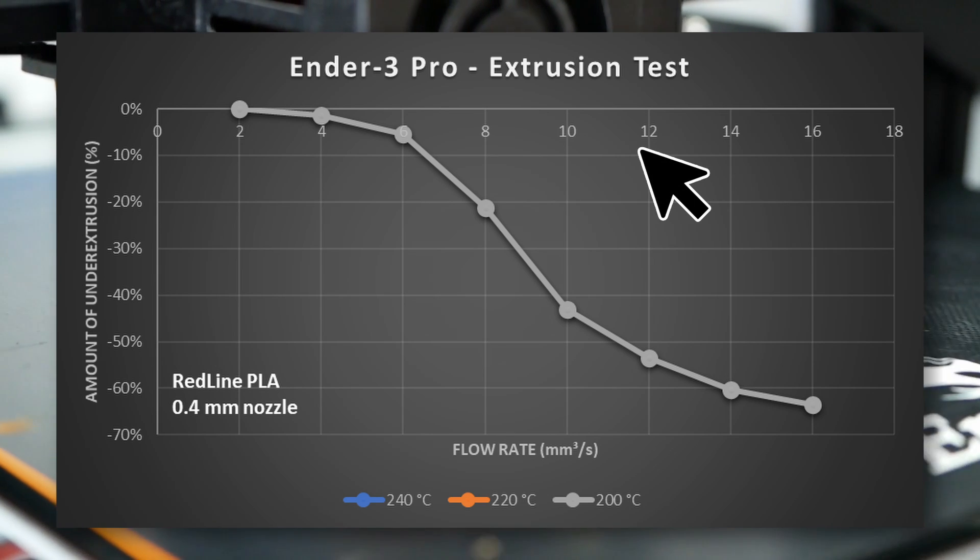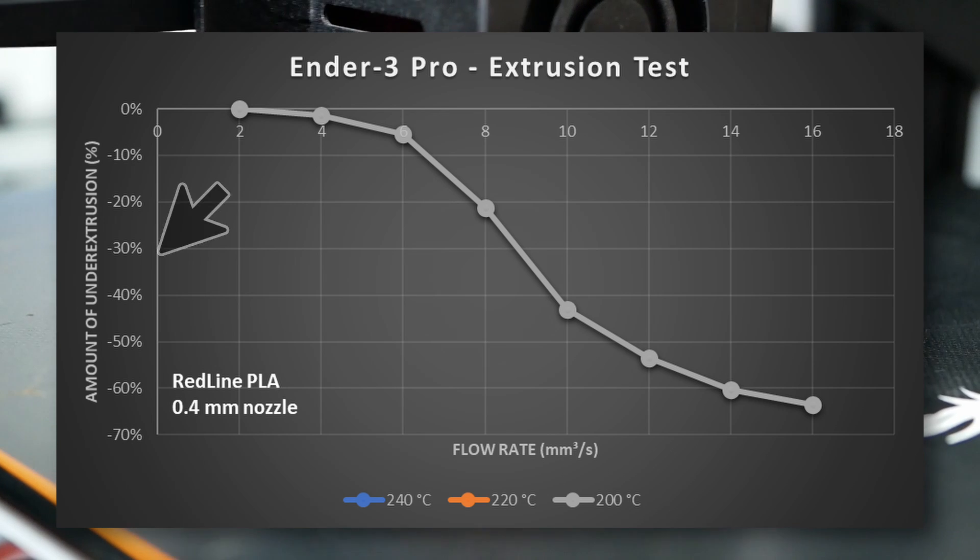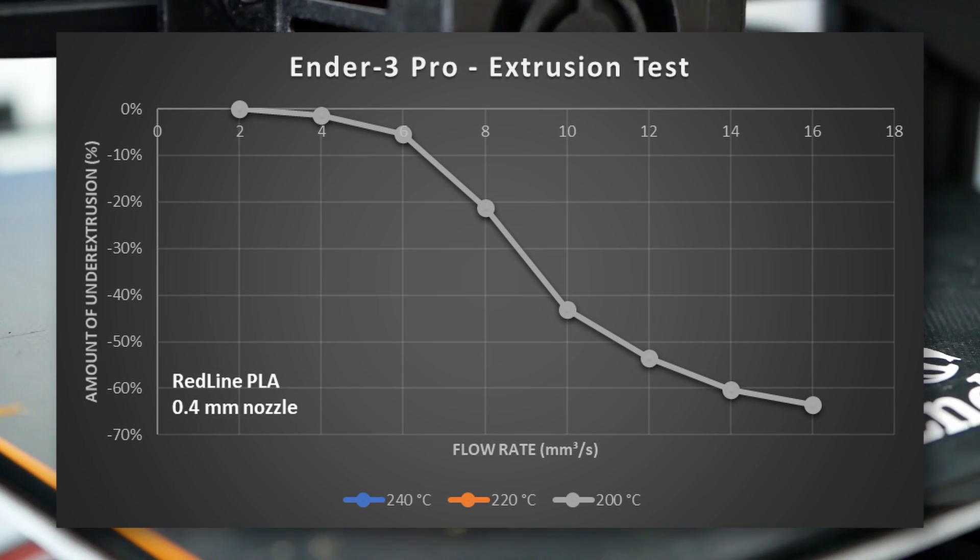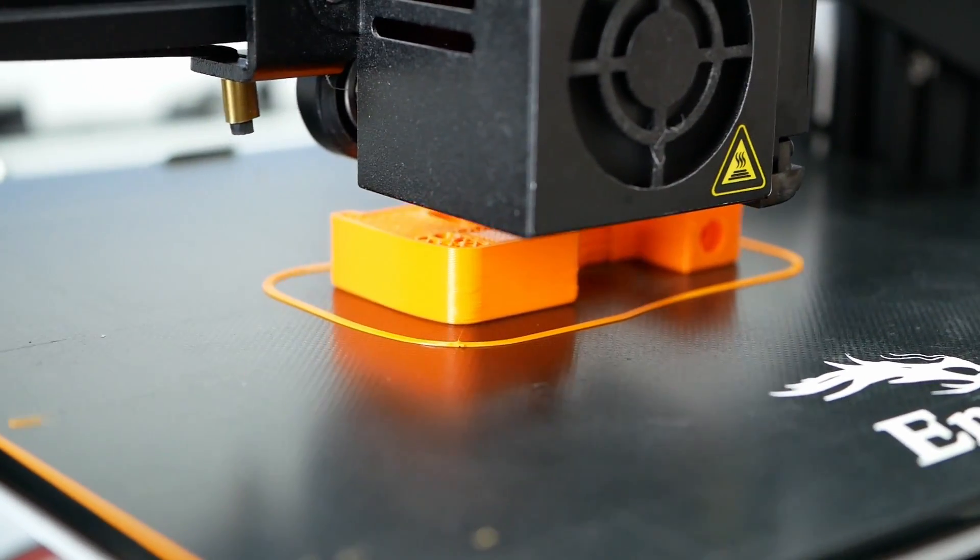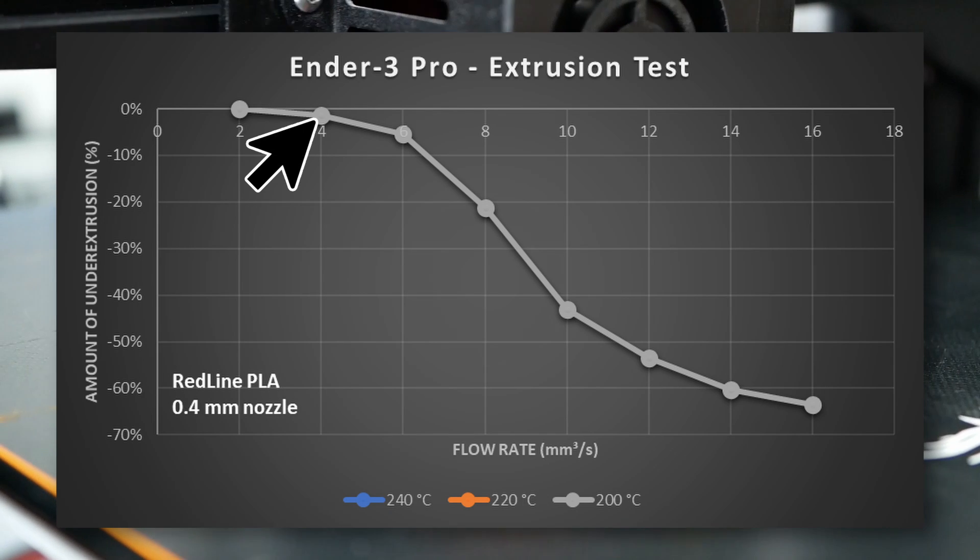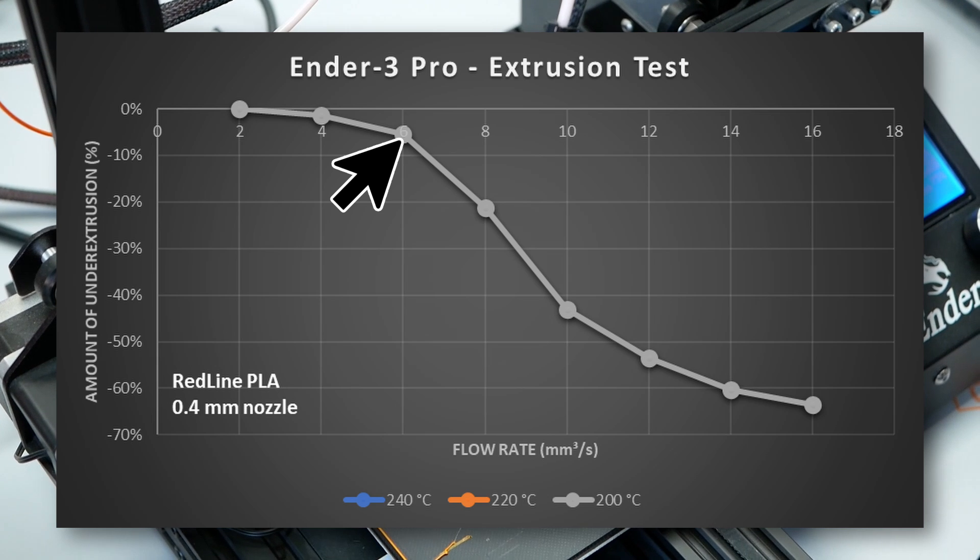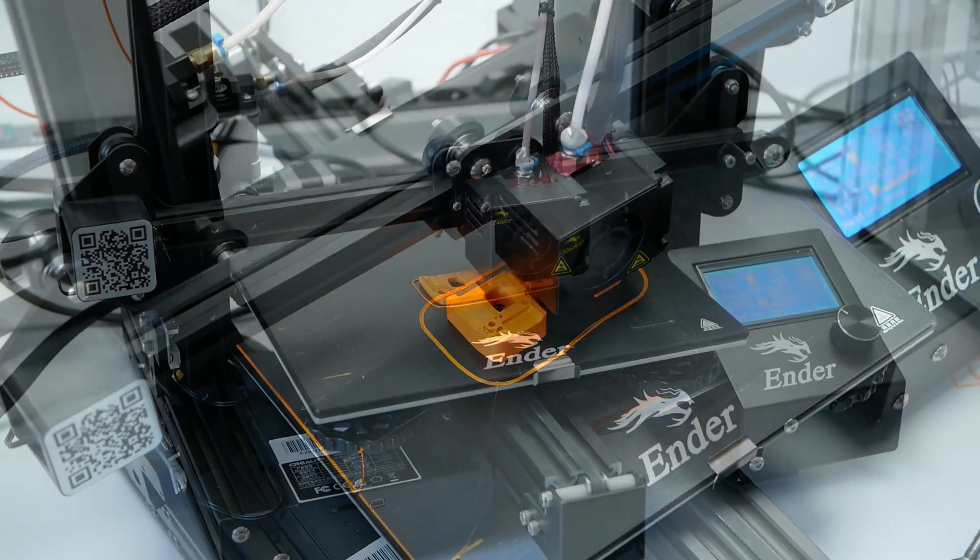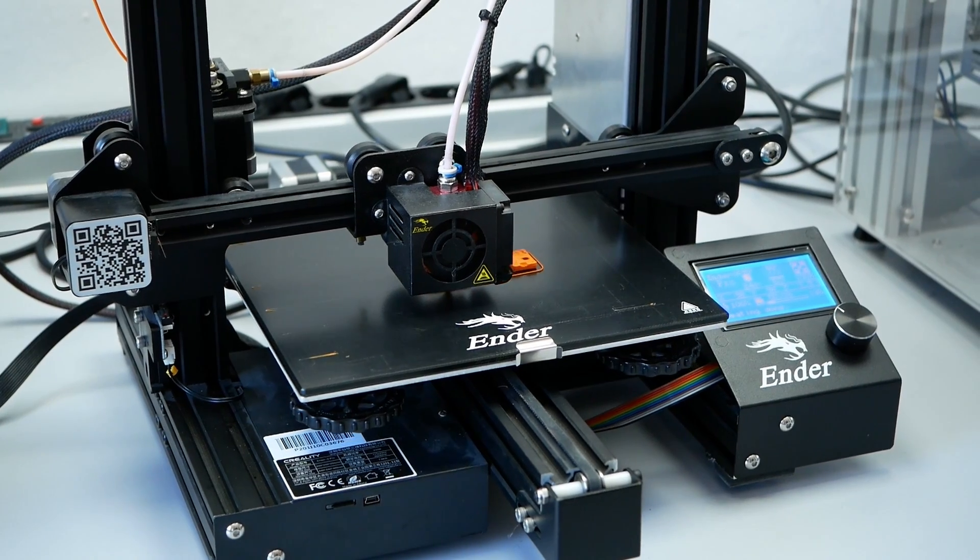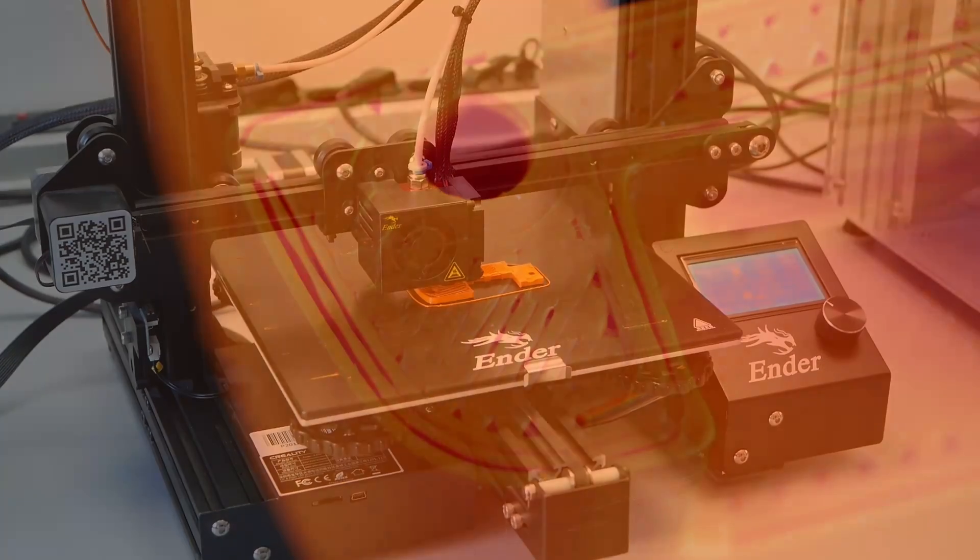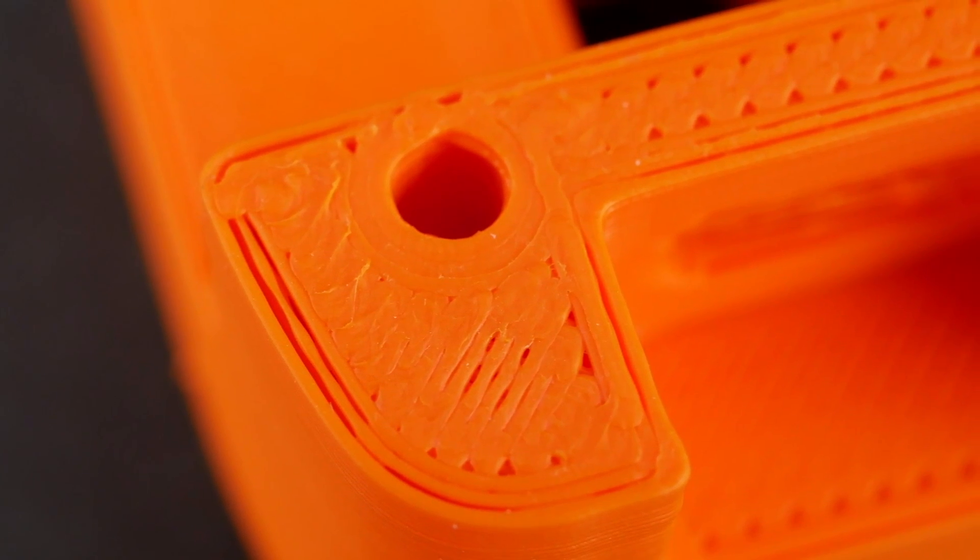This can be nicely shown in graphs like this one that I regularly make. Here we see the flow rate on the x-axis, the amount of expected underextrusion on the y-axis. This was done on a basically stock Ender 3 Pro using PLA and a nozzle temperature of 200 degrees Celsius, which is common with many profiles. The thing that's important here is that the flow remains relatively constant up to 4mm³ a second, slightly drops to around 5% underextrusion at 6mm³ a second and then just severely plummets after that. You can and actually should create these plots yourself if you want to print faster than the standard profiles you usually receive with your machine. They will tell you how fast you can go without creating huge gaps between the top layers or your perimeters.